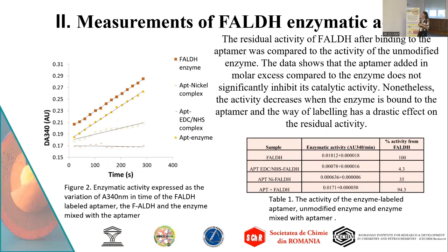After that, we needed to measure the enzymatic activity of our complex, because it's a very important part of our compounds to have enzymatic activity, so we can use it later. In that graph, you can see the enzymatic activity, firstly of the enzyme, then the aptamer with the enzyme, not our compound, just aptamer and enzyme. Then the two compounds that we obtained, the compound with nickel chloride and the compound with EDC/NHS. We wanted to measure the enzymatic activity of the enzyme with the aptamer to see if the aptamer inhibits the enzymatic activity, and it truly inhibits a little bit, but not in a great amount.